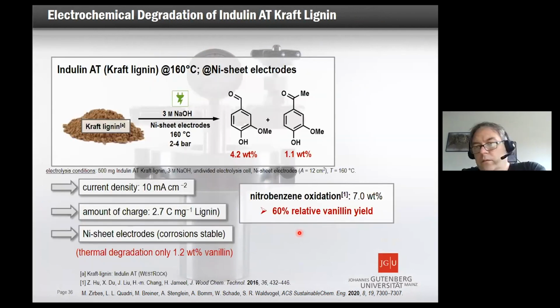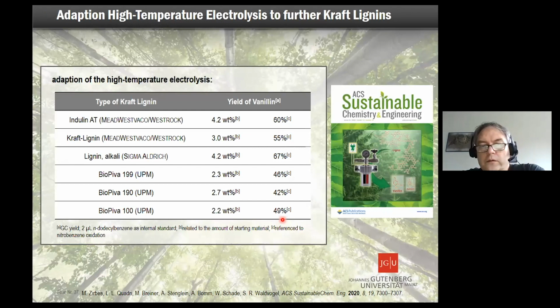Then we went to different Kraft lignins, and one of the best we could use here was Indulin AT. And here with the nickel sheet electrodes, you see it even went to 4.2 weight percent, and concurrently the acetovanillone also formed. You see that the number is very similar: almost 60% relative vanillin yield compared to what the nitrobenzene oxidation provides. At that point, we had a look, and here you see summarized the different yields we had, which was also published last year in ACS Sustainable Chemistry and Engineering.